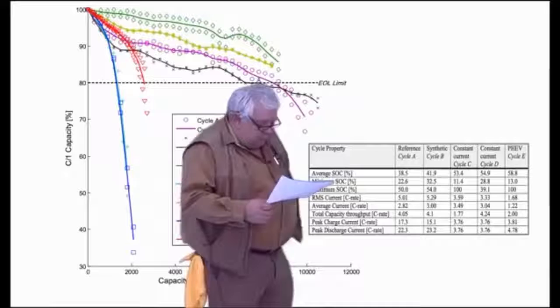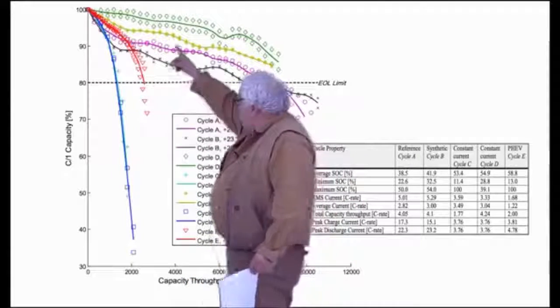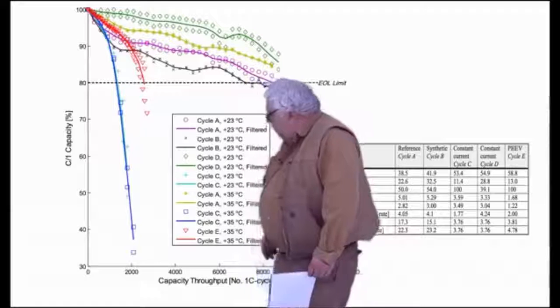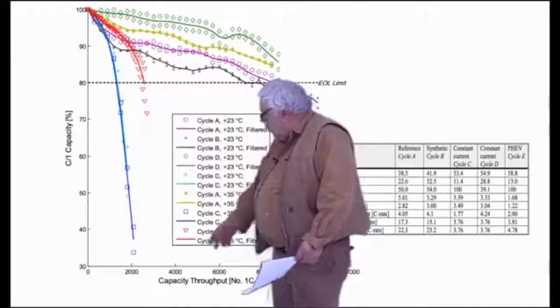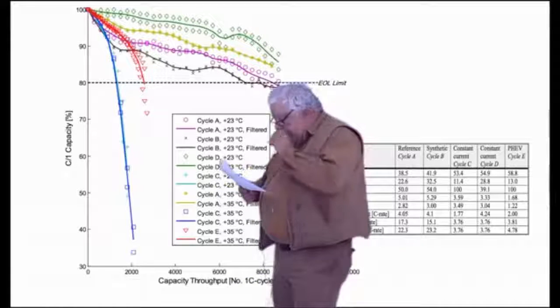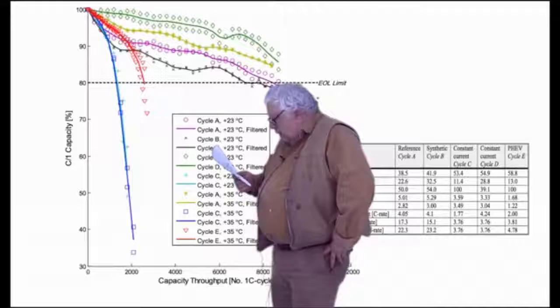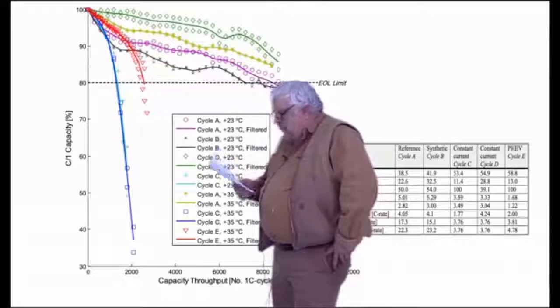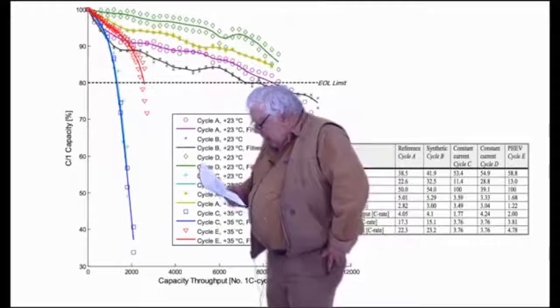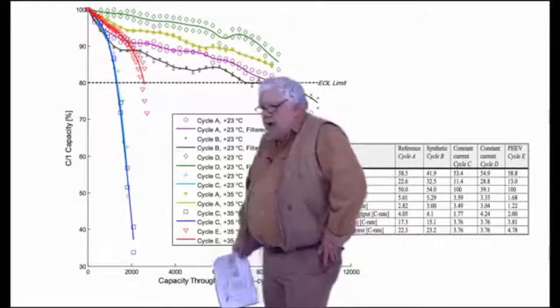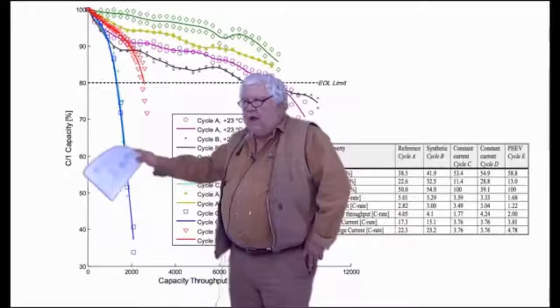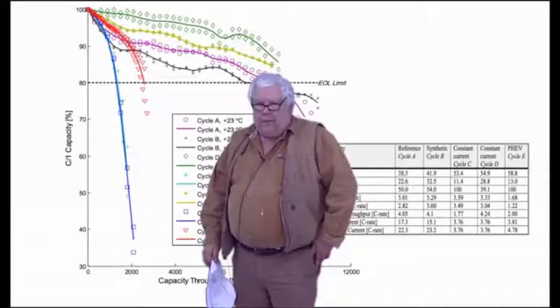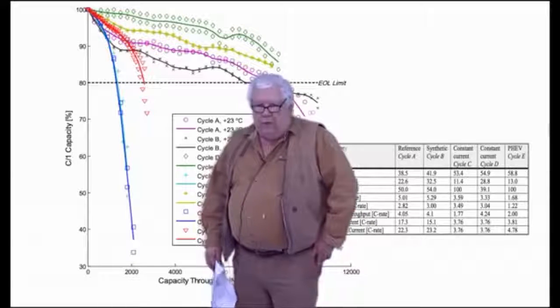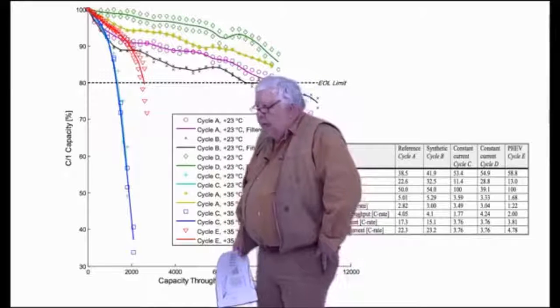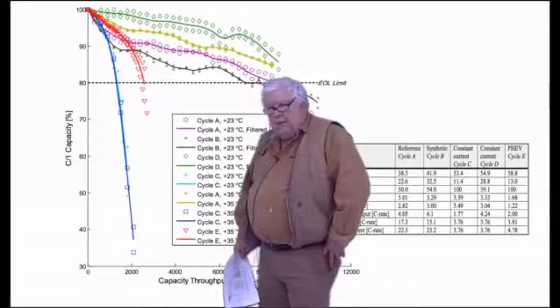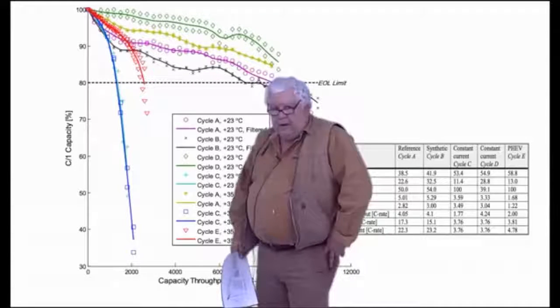You will see also a cycle C, and it's over here in a blue and a kind of a teal that you can barely tell apart. It just looks like a dark blue line. That is cycle C, which is from about 11.4% state of charge to 100% state of charge, and at a constant current of charge and discharge of 3.76 C. Now this is how you normally see a cycle testing done, is 100% down to some low value or even 0% at a fixed rate. This is kind of a high rate at 3.76 C. You'll often see this done at 1 C.